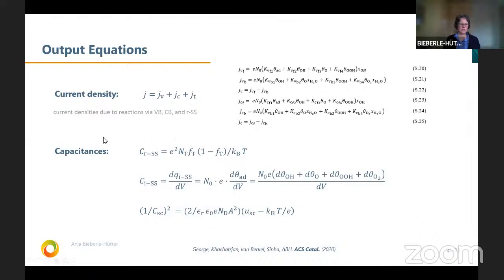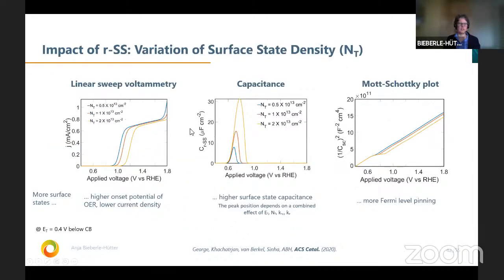Here I show the main values that we calculate in the following. So we use the capacitances as values that we compare now when we change the surface state density. So you see here linear sweep measurements. We increase the surface state density. When we have more surface states, we get a higher onset potential and lower current density, which makes sense. Also with the capacitance, we see when we have more surface states, we get a higher surface state capacitance.